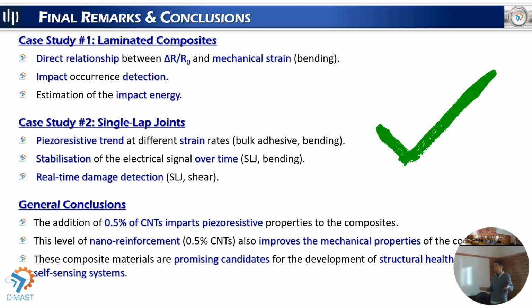First, the addition of the carbon nanotubes imparts piezoresistive properties to the composites, which was the main objective of this additivation. Second is what I call the double positive effect of this additivation. The carbon nanotubes in this percentage of 0.5 wt% also improve the mechanical properties of the composite, so it is an additional good result of this manufacturing process. And as a final conclusion, for now, we would say that these composites are really promising candidates to produce structural health monitoring self-sensing systems based on these materials.